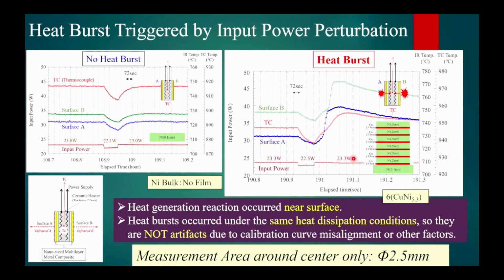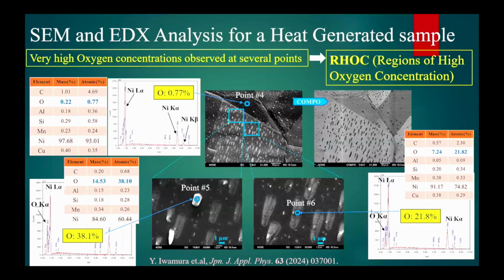So we think this phenomenon is correlated to the motion and diffusion of hydrogen in the nanolayer region. But in this data, we measured the surface temperature only over a small 2.5 millimeter region. We use a 25 millimeter sample, so we only measured around the surface, just 2.5 millimeters.